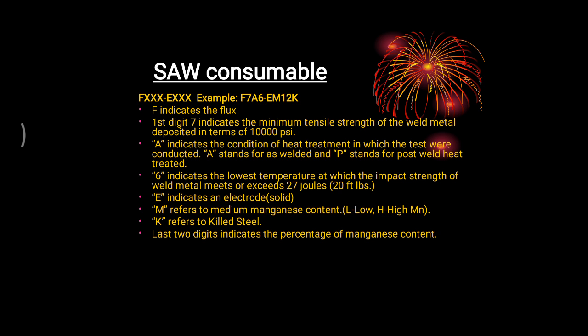So in SAW the electrode has been defined in the following way. The first digit, see the example, 7, indicates the minimum tensile strength. The next indicates the condition of the heat treatment in which the tests were conducted. The A sign stands for as-welded, and P stands for post-weld heat treatment. And the 6 indicates the lowest temperature at which the impact strength of the weld metal meets or exceeds 27 joule.